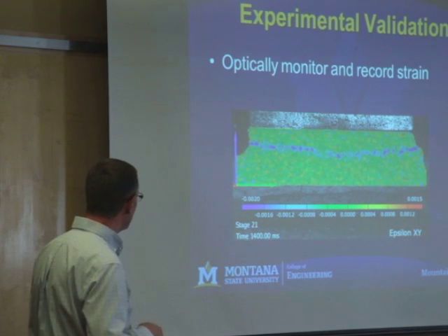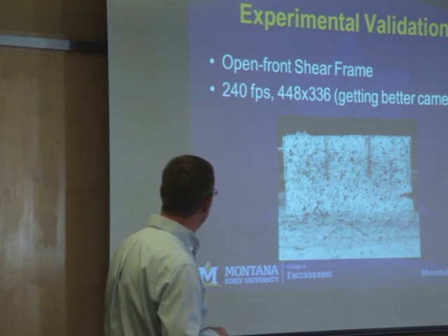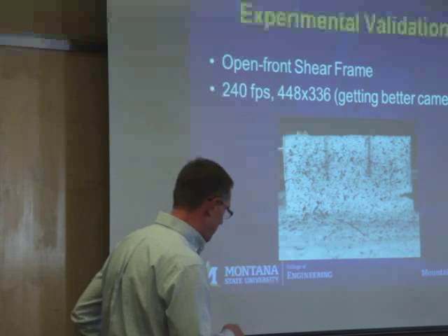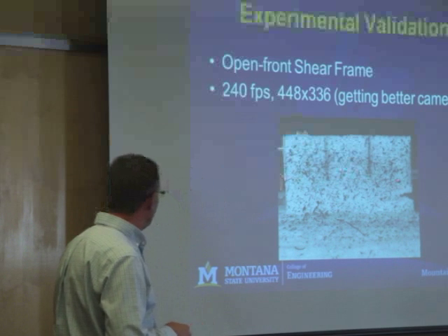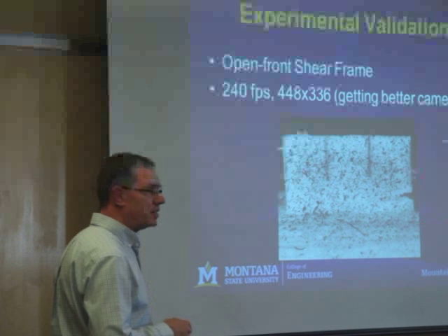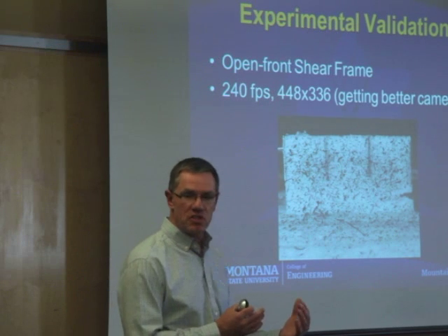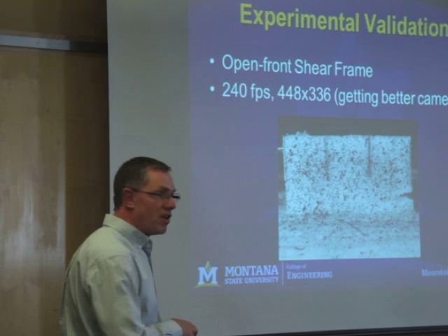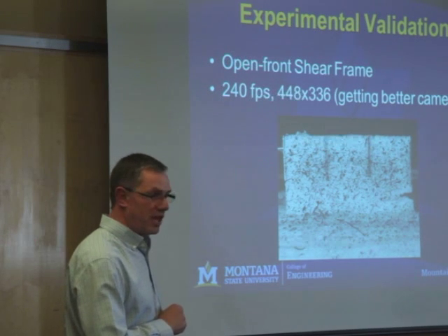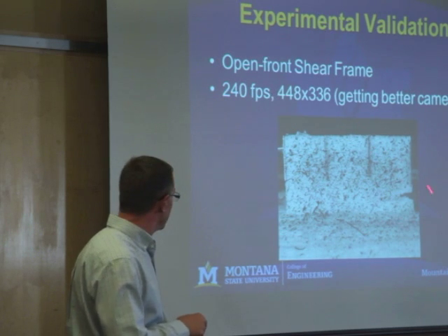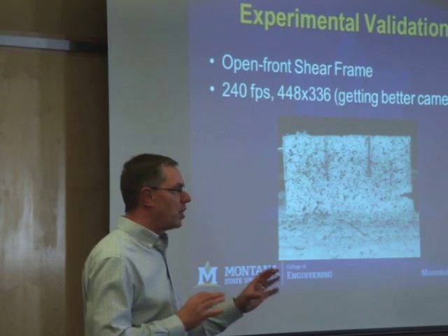Okay. One of the things we have to modify for this project is a couple of things. One is, I'll talk about it here in a minute, we need to track everything that's going on here, right? Because if I take a load cell and I push on this, and some of these grains, I create some strain up here. Maybe the weak layer's down here, but I create some strain up here. That's energy that went into the system that's not going into fracturing my weak layer. So we have to account for all that. And so we've designed this new open-front shear frame so that we can pretty much track all the particles that are going on in there.